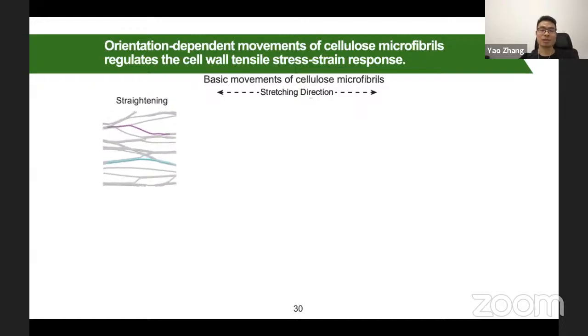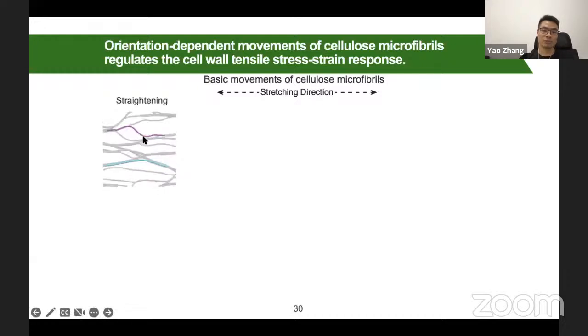Now we try to understand how this cellulose fiber can generate this unique stress-strain response. We look at the orientation change of the fiber and also at the movement of the fiber. And we found there are several types of movement of this fiber. The first one is straightening. What does that mean? When you stretch your cell wall, some fibers just become more straight.